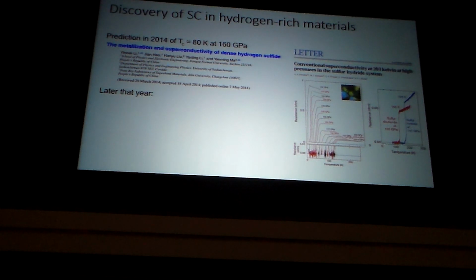And believe me, these are very difficult experiments to do. So you cannot do a lot of the traditional experiments you would do to verify superconductivity, like magnetic measurements. The Meissner effect is usually very important to measure. And these experiments have now been confirmed by other groups, which is very important in any science. All right, so now we have hydrogen sulfide hydride, a hydrogen-containing compound that has a very high TC. So of course there are now people working on this. There are maybe 3 or 4 groups in the world, maybe 5, that can put high pressure onto things like this.